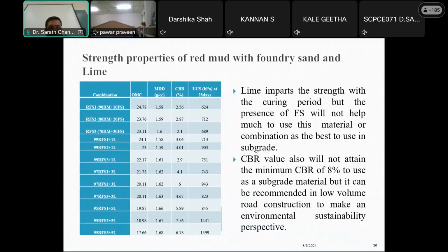The strength properties of red mud with foundry sand and lime improve with the curing period, but the presence of foundry sand will not help much, so this combination is not the best to use in subgrade. The CBR value also will not attain the minimum CBR of 8% required for a subgrade material, but it can be recommended in low volume road construction from an environmental sustainability perspective. So though we don't achieve the 8% CBR here, this combination can be used. For example, in localities where red mud is highly available, they can construct low volume traffic roads.